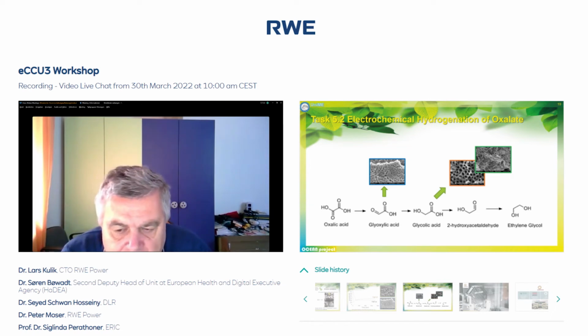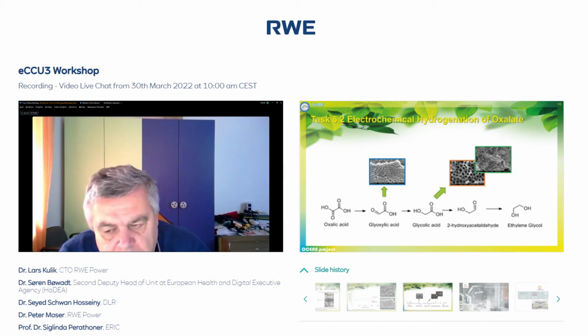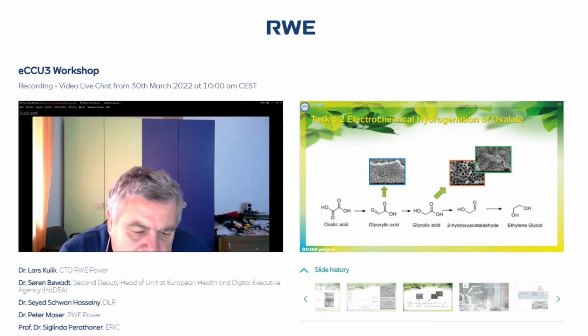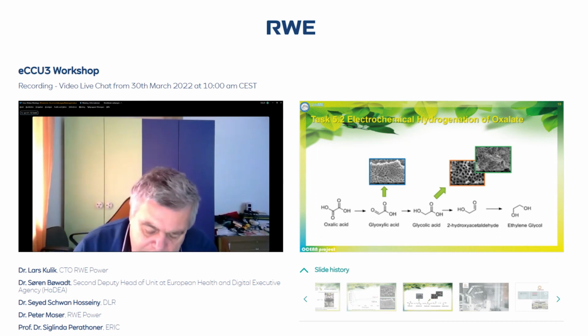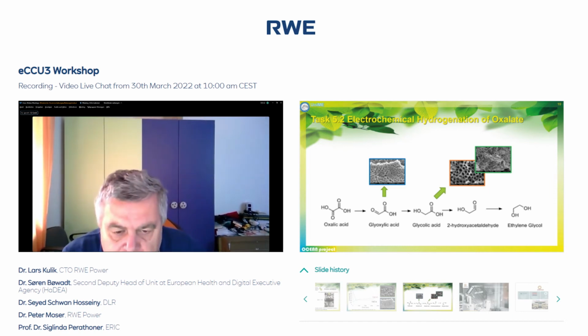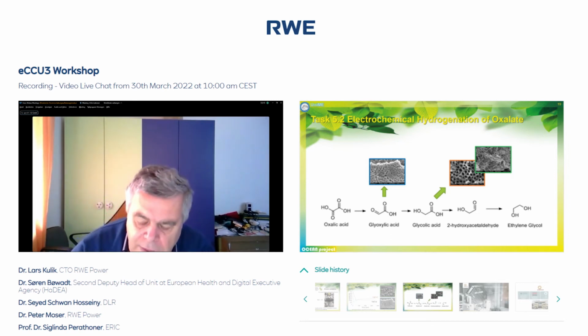And this is exactly related to the number of defects, the oxygen vacancies, which are formed in the system. You see that you can obtain a kind of linear correlation between this amount, which can be determined by XPS, for example, with an example in the inset, and the yield of glycolic acid. So this is just to give you an example that there is also good science behind the development of this system, and you can optimize and choose. For example, depending on the type of nanostructure that you obtain, you can maximize the formation of glyoxylic acid or of glycolic acid.